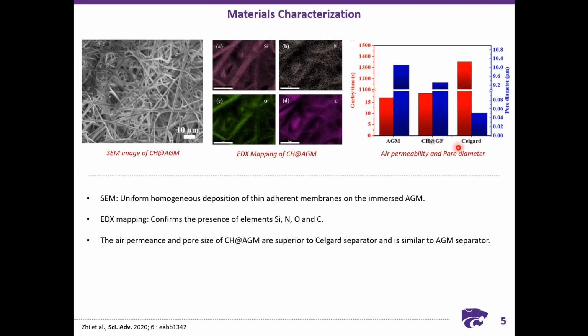AGM. The authors have probably used an AGM separator which is quite thick, around 1.3 mm. They might have chosen this instead of Celgard, which is mostly used in lithium ion batteries currently and has a very low thickness, because of these parameters, maybe the air permeability and other parameters.